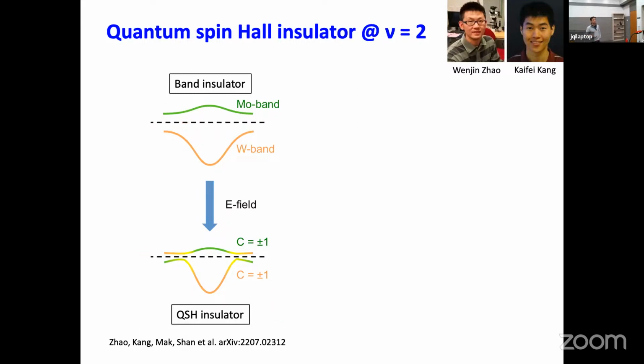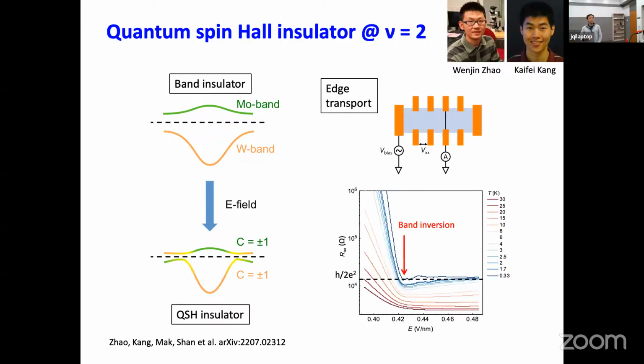Okay. And this is a transport experiment where we measured the 4-point resistivity as a function of the electric field, keeping nu equal to 2. This is the measurement geometry shown at the top. We pass current in the longitudinal direction, and then we measure this 4-point voltage here. The other 2 sides of the electrodes are also grounded. Now you can see the data at the bottom, which shows the resistivity at different temperatures. And this is the band inversion point, at this particular electric field near 0.42 volt per nanometer.